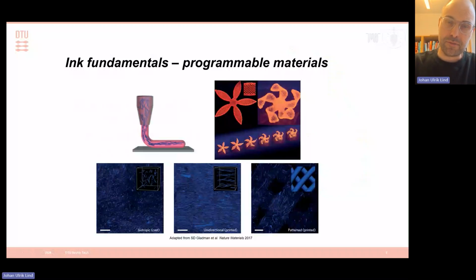But we can also play a little bit more with the formulation of these materials. One classical example that we will return to here is what some people call 4D printing, where you use the printing process to induce some kind of organization within your printed material. This example was one of the first, where embedded cellulose fibers direct the swelling properties of printed patterns. So when you print a pattern, swelling in a liquid will be controlled by the orientation of the fibers.